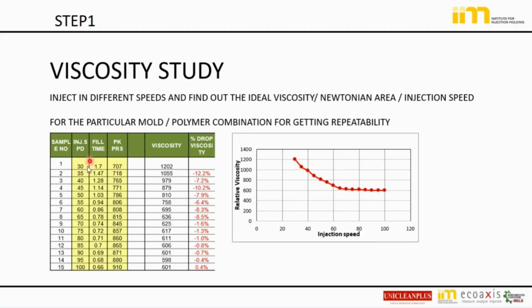I started with an injection speed of 30, a slower injection speed. The machine will show the actual filling time based on the resistance of the machine, the screw, bush, runner, and the part. We note that down in this spreadsheet. Then with respect to that speed, what is the pressure? The peak pressure when it is filling 90 percent, the machine will show that. We just write it down. The viscosity will be automatically calculated. There is a background calculation going on, but from this we'll get a viscosity.